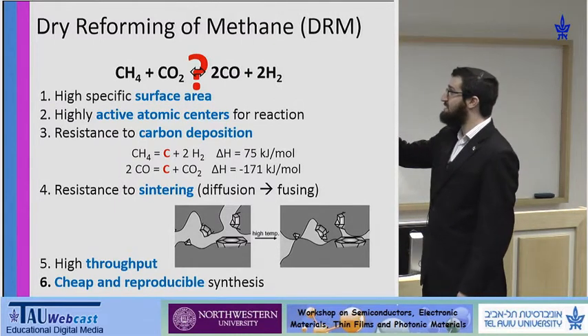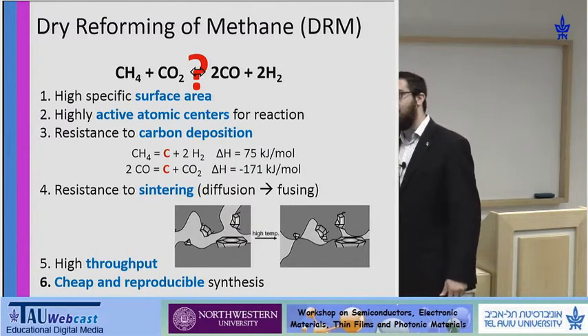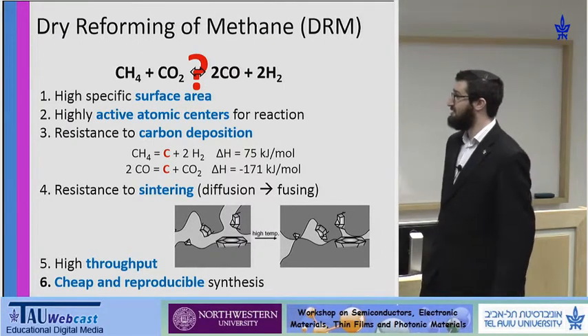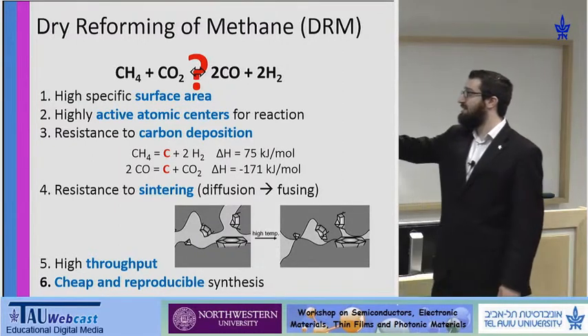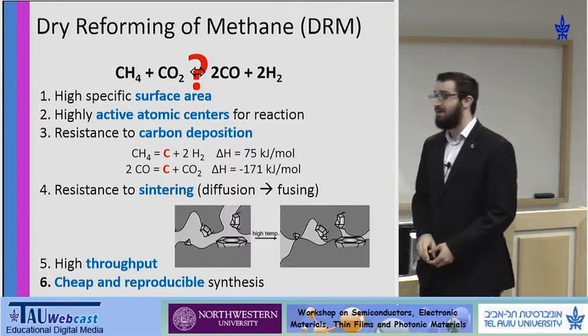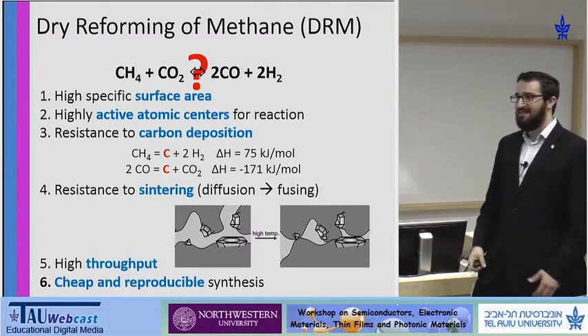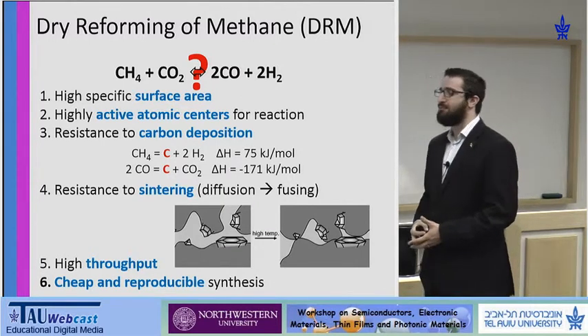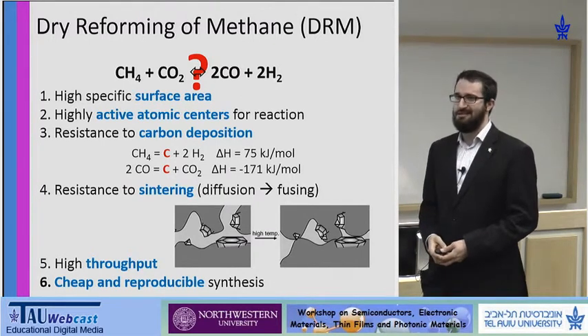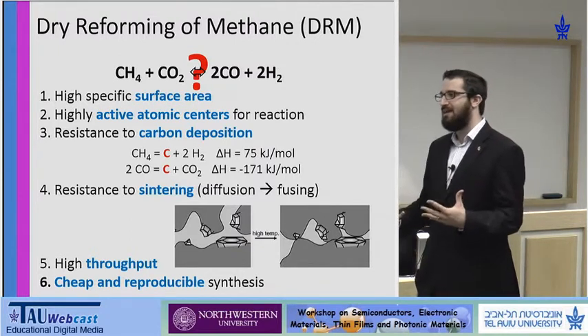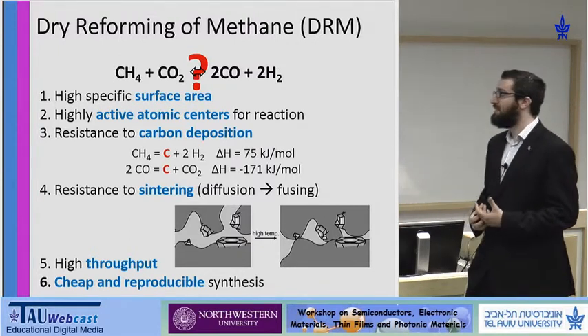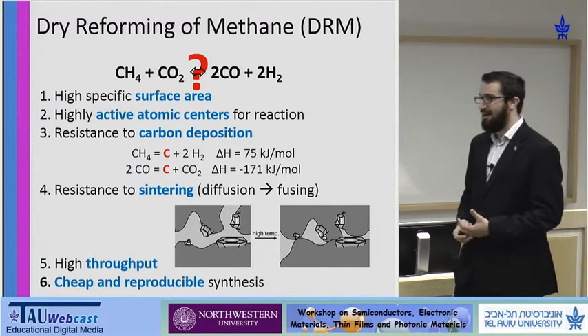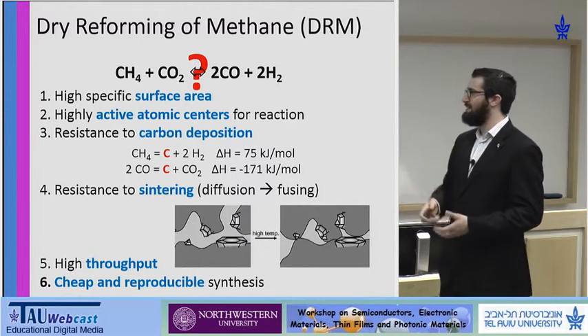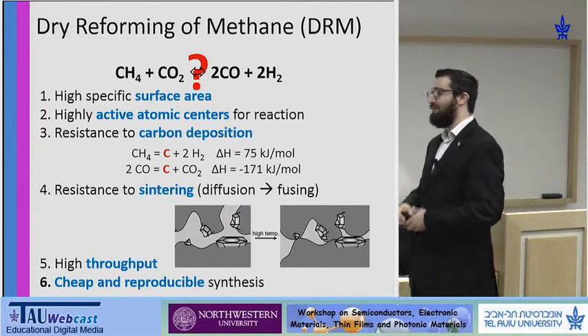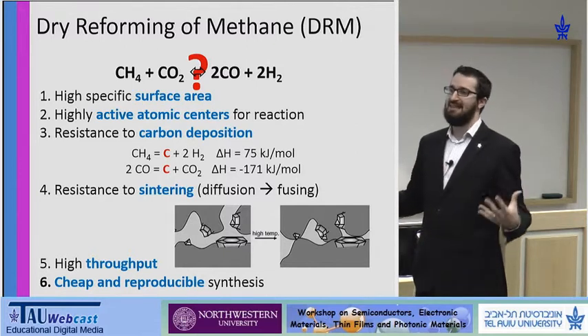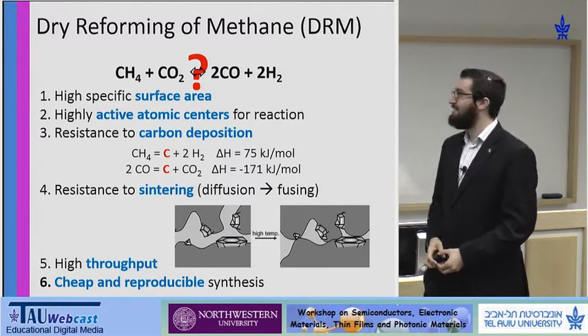Obviously, we want high specific surface area, very active atomic centers, and what is most key, resistance to carbon deposition. We see here two alternative pathways that carbon monoxide and methane can take on the surface, leaving behind solid carbon. This process is called coking, and this is the primary reason why methane dry reforming is not industrialized today. You have very, very active catalysts that can do industrially relevant rates, but they all suffer from coking, they have short lifetimes, and this carbon deposition in many cases is not reversible. So what we're interested in developing is coke-resistant catalytic surfaces in order to industrialize methane dry reforming.